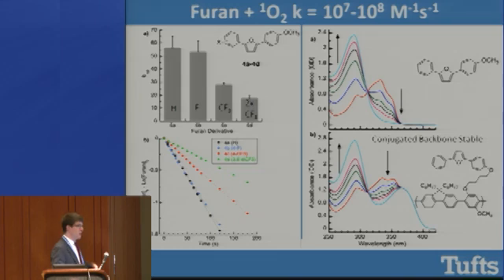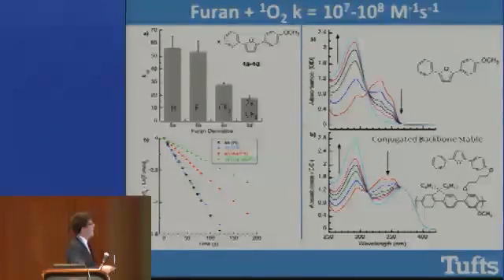Moreover, something that we worry about greatly when using organics and exposing them to reactive oxygen species like singlet oxygen is degradation of chromophores that we necessarily don't want to degrade. And so this is something we're always cognizant of and looking out for. What you're looking at here in the upper right is the UV spectra of this diaryl furan as a function of time upon exposure to singlet oxygen.